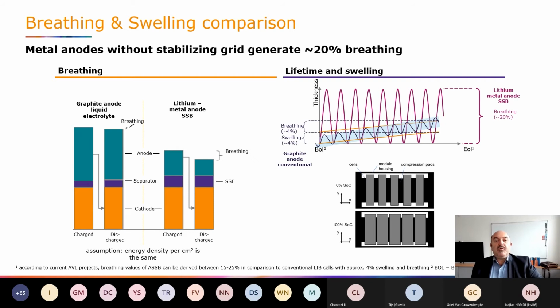We have to use different mechanisms, such as special compression pads, that can stand these strong volume changes in the cells. Of course, the mechanical fixation has to be strong enough to bear the pressure coming up from these breathing effects. Also, dynamical systems, mechanically or using isostatic liquid pressure, could be imagined, but seem to be much more complex.